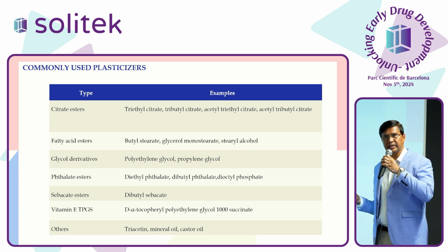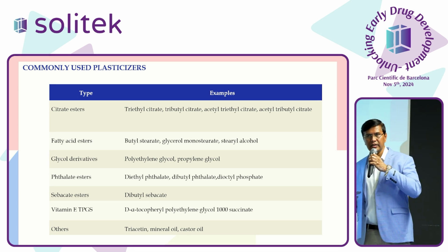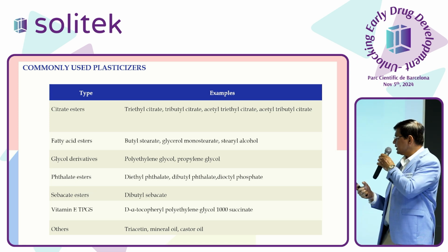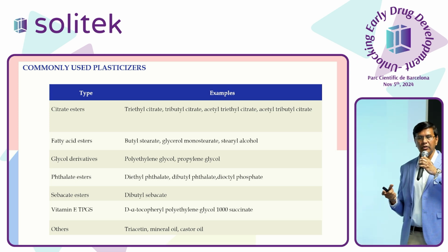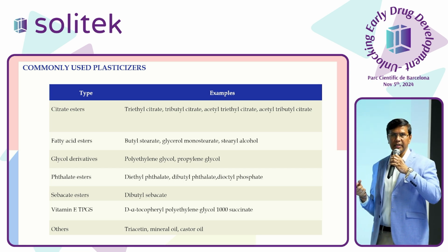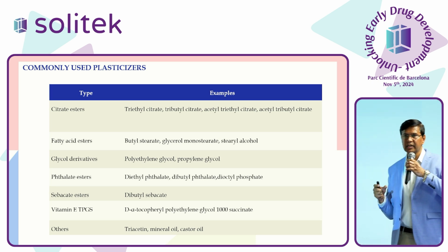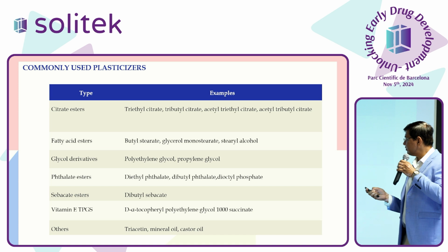With this 10% or 15%, you can reduce the processing temperature, or in other cases we can increase the solubility maybe 10 or 15 times by using this surfactant. For example, if HPC alone gives a processing temperature of 200 degrees Celsius, with TPGS the processing temperature may be around 150 to 160, and the solubility enhancement may be 30 or 40 times that of the single molecule.